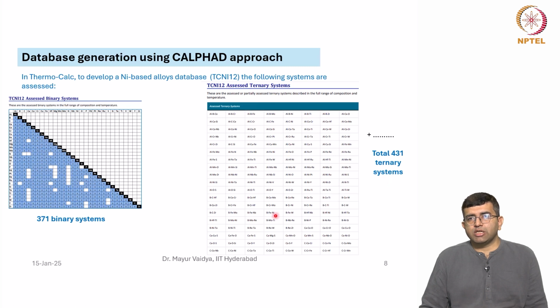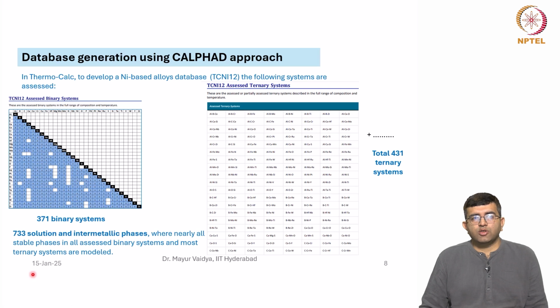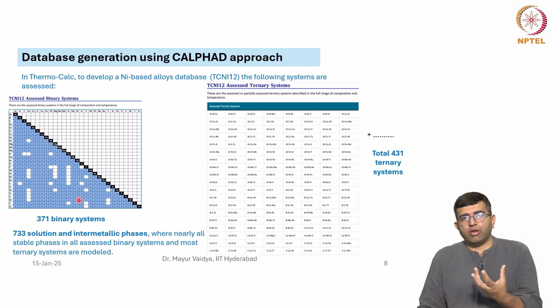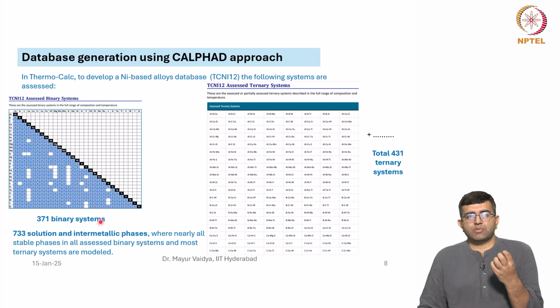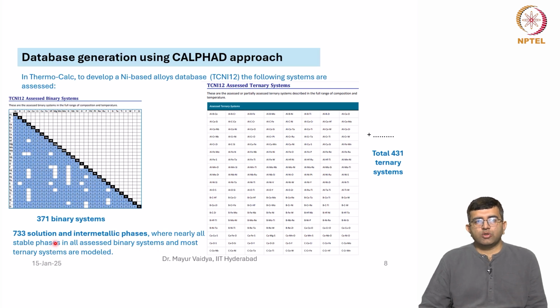So, various combinations are assessed, and totally around 733 solution and intermetallic phases were modeled, nearly all stable phases in all assessed binary systems, and most ternary systems. So, you can see that to create one database, how much of the effort goes into the assessment of a number of binary systems, a number of ternary systems, and then so many of the solution and the intermetallic phases and so on.